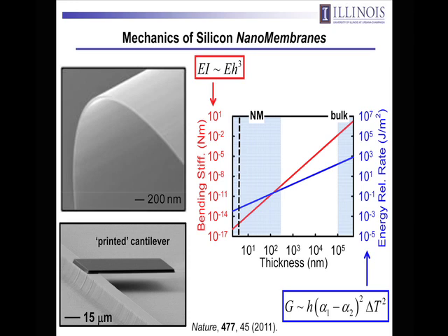That's very, very stiff. If you take that silicon wafer and you have a way to shave it thin all the way down into sort of a nanoscale membrane, so maybe 10 or 100 nanometers in thickness, the bending stiffness can be reduced by 15 orders of magnitude because of that cubic dependence. You go from 10 newton meters to 10 femtonewton meters just by reducing the thickness. And that's not a quantum effect, but it still has a qualitative impact on the way that you think about the mechanics of the material. So here's an example of a 20 nanometer thick monocrystalline semiconductor grade sheet of silicon, a nanomembrane of silicon. You can see it is quite floppy because of that very, very low bending stiffness.